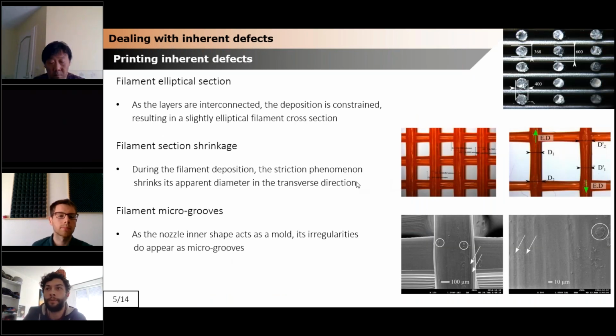Okay, I will now cover the defects that actually occur during the 3D printing of such a microlattice. The first one is that during the deposition, since the nozzle is connected to the previous layer that has been printed, the deposition is actually constrained. So the cross-section area of the filament is not going to be perfectly circular, but rather slightly elliptical. This is pretty well observed during all of this FDM process, but you cannot actually consider a perfectly cylindrical cross-section area. Another effect that appears during the deposition is a striction phenomenon, as seen on the orange pictures.